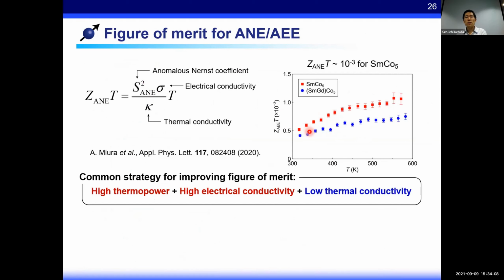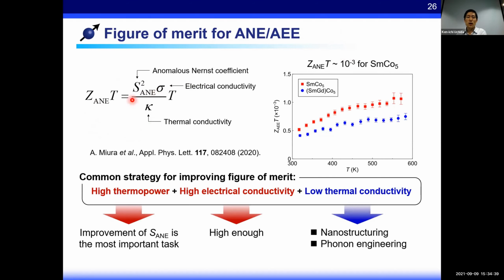So even for samarium cobalt 5 and CMG, cobalt manganese gallium, showing the large anomalous Nernst effect, the dimensionless figure of merit is still on the order of 10 to the minus 3. The definition of the figure of merit for the anomalous Nernst effect is very similar to that for the Seebeck effect, where the Seebeck coefficient is replaced with the anomalous Nernst coefficient here. Therefore, the strategy for improving the figure of merit is also similar. The materials should have a higher thermopower, higher electrical conductivity, and lower thermal conductivity.